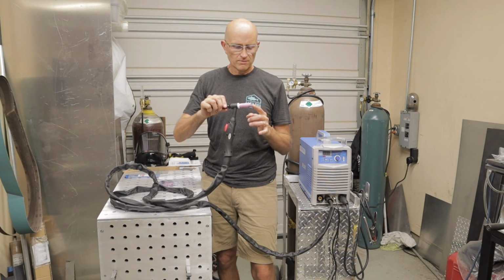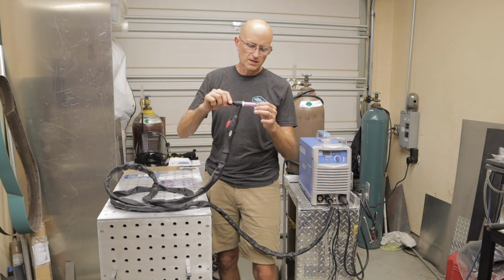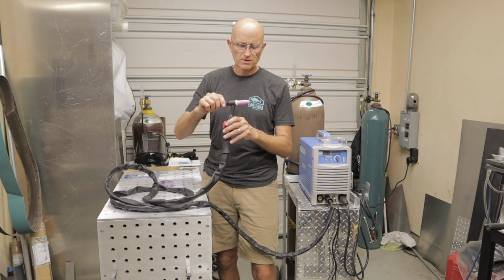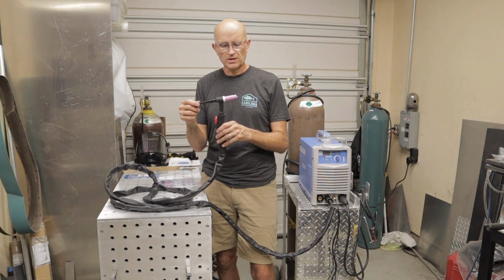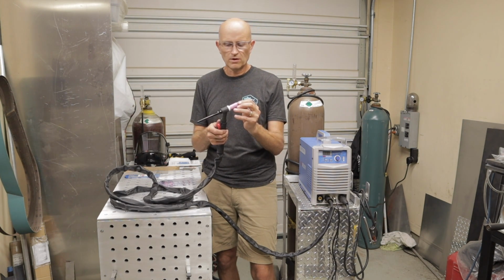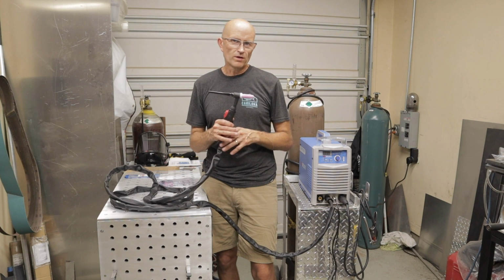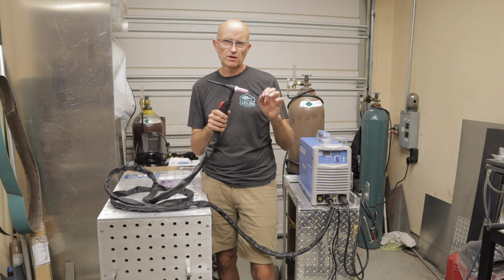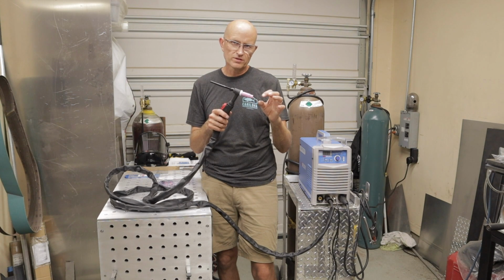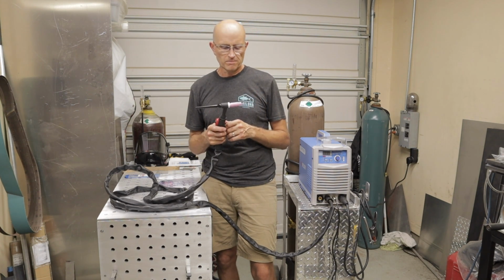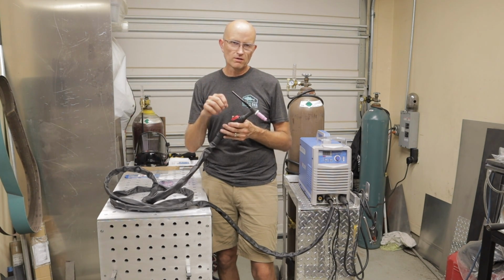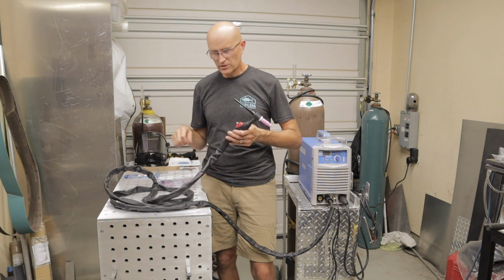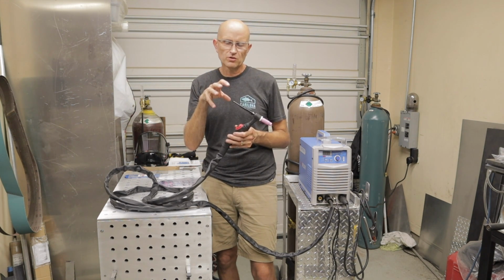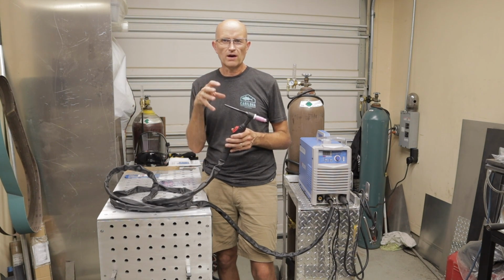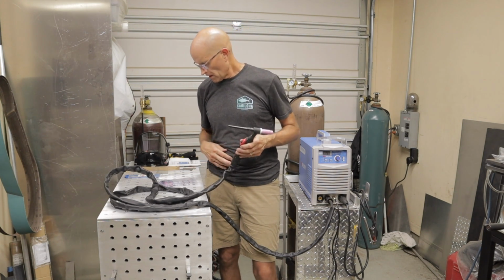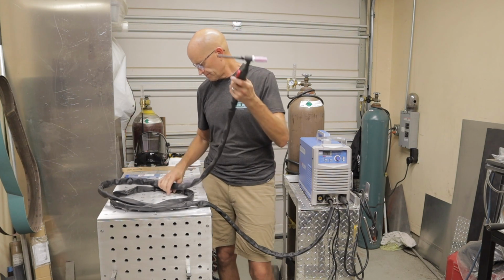I then set my tungsten to stick out usually about 1/4 of an inch. Sometimes I go a little bit less, sometimes a little bit more, depending on whether I'm welding down into a corner, a fillet weld with aluminum. I usually have a little more stick out. If I'm welding small, thin material on the bench, a lot of times I'll pull it back so I can get a really good shielding cone around the tungsten. Alright, so we're all set up with our torch.